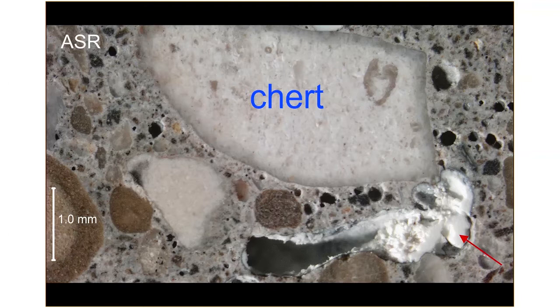This is a chert aggregate particle. It's one of these larger pea gravel sized particles, and we see the gel extruding into the void. It's a big, long, banana-shaped void below it, and you can see all the gel that's extruded in there. So this pavement's not immune to ASR, but there were just not that many aggregate particles, and it's not producing wholesale bulk expansion of the pavement.